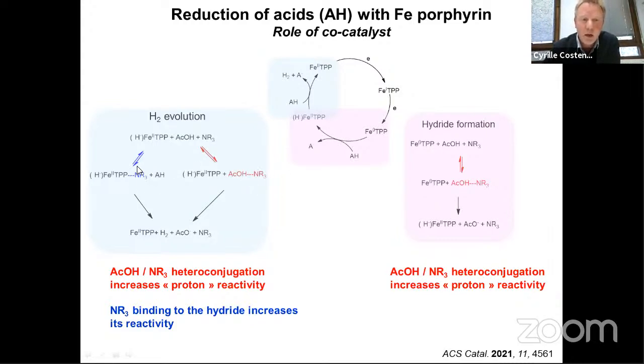But we have also observed that a non-basic species can also accelerate the rate. And the proposition is that if you have a ligand which is able to bind in a trans manner, probably on the iron hydride porphyrin, you will make this hydride more reactive and you will increase the reactivity. So this means that a co-catalyst can be just a ligand that will bind an intermediate in the mechanism. And because here, as I said previously, the second step of the process, so the reactivity of the hydride, is slower than the first one, you have accumulation of the hydride in the diffusion reaction layer. And so if you put a co-catalyst in the diffusion reaction layer, this will activate this intermediate and make the process faster.